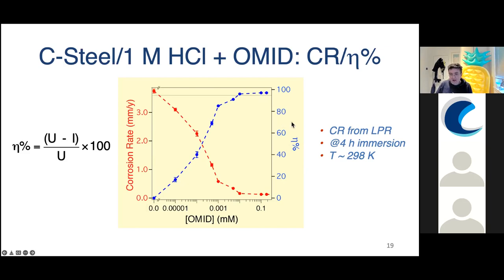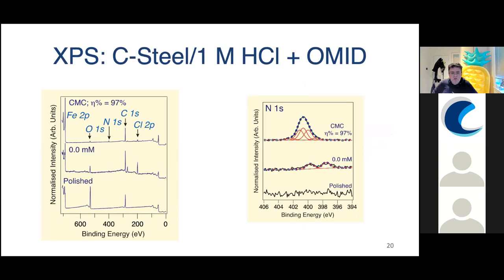CMC, the critical micelle concentration, which is here, is about 97%, but you can see that even an order of magnitude below the CMC, we're already getting the molecule to work very well, and this line here is 95%. So in this case, you don't really have to be at CMC for it to work well, but it does work well at CMC, and we're going to be focusing on that in the latter part when I'm characterizing these systems. So let's look now at characterization of carbon steel, one molar hydrochloric acid, plus OMID.